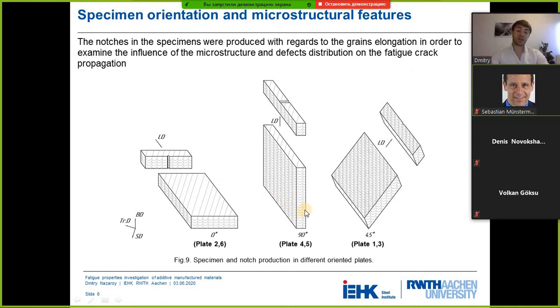For plates 4 and 5, which were printed perpendicular to the flat surface, these plates and specimens are called vertical specimens. Here the notch was produced in such a way that the crack propagated coaxially to the building direction. With regard to plates number 1 and 3, the crack was tilted 45 degrees to the building direction.